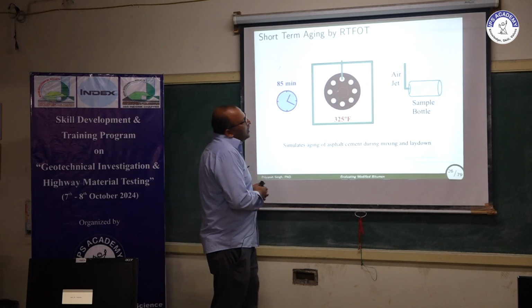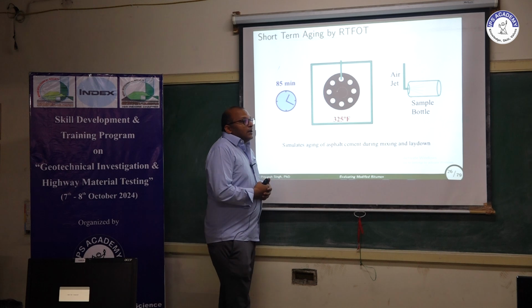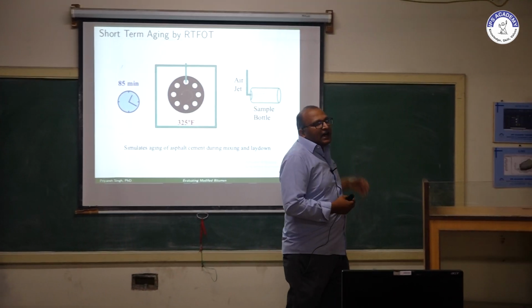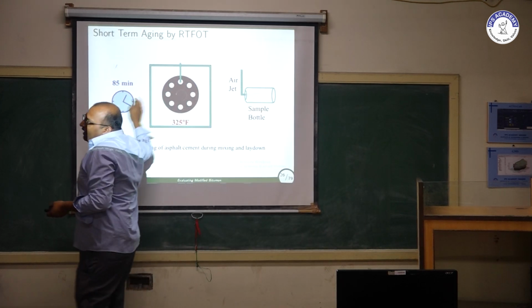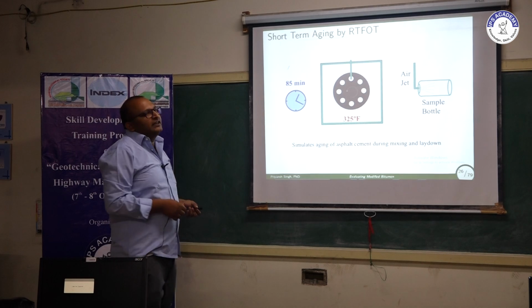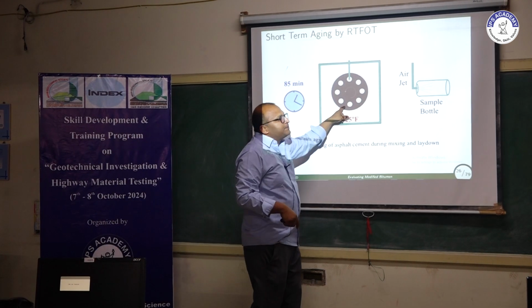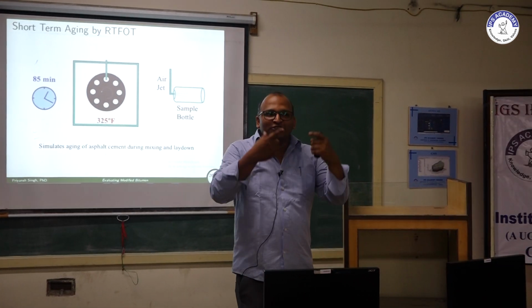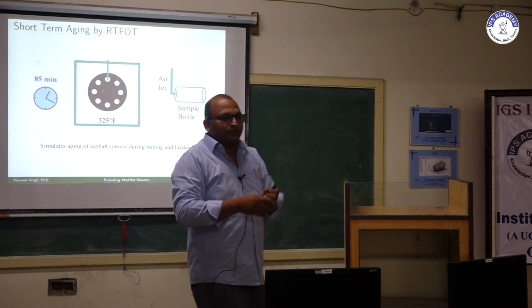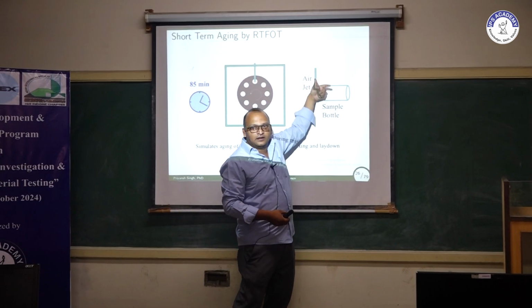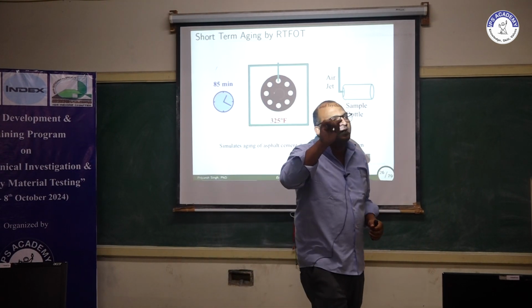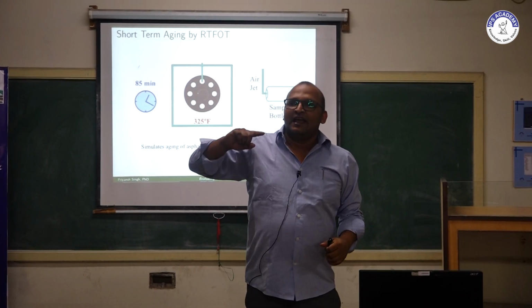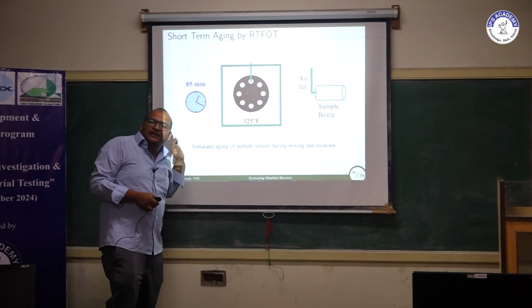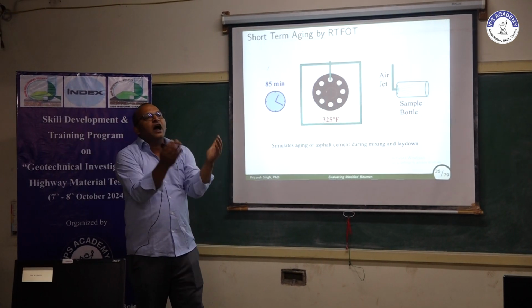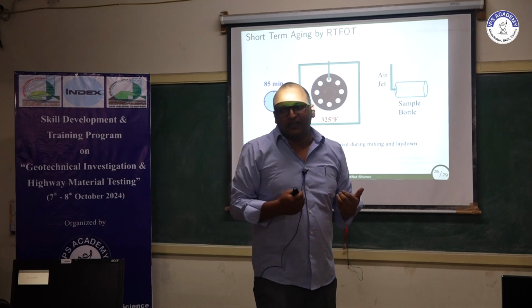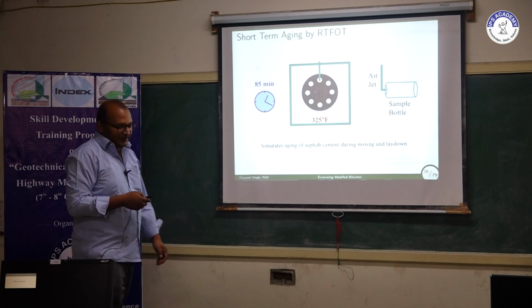Now in this rolling thin film oven test, you have a vertical cage in which you put your samples. We put our samples in some glass jars, and these glass jars are kept here, and we blow air at 163 degrees Celsius for 85 minutes inside this oven. During this process, this cage will rotate at the speed of 15 rpm, and because of this rotation, the binder will rotate around the tube. That will create a very thin film of binder on the surface of these jars, and that is why the name came as rolling thin film oven test. And because the surface area is more, we achieve aging in a shorter time period. So that is why the test takes only 85 minutes to complete.